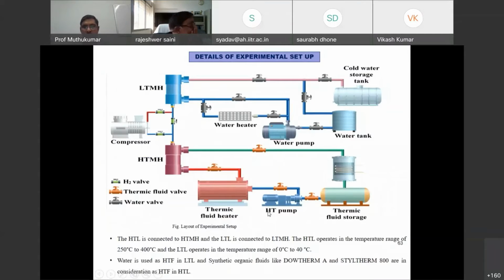So this is the proposed experimental setup. We have both the high temperature loop and the low temperature loop, and from the low temperature loop you can get the cooling output. The high temperature loop you can use for storing the heat, and then upgrading the heat from about 350 degrees Celsius to about 450 degrees Celsius.